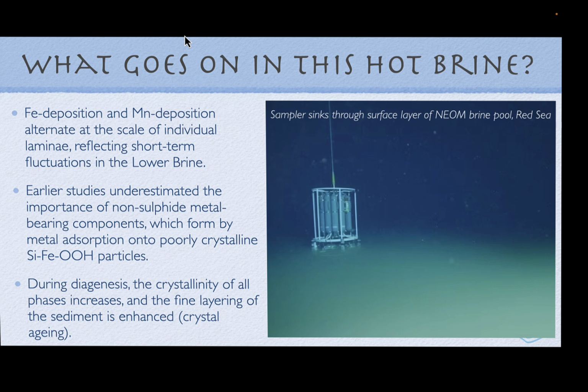It's become obvious in the last decade that earlier studies underestimated the importance of the various non-sulphide minerals as metal-bearing components, where the metal absorption is forming onto polycrystalline silica iron hydroxide particles. Remember back to the brine chemistry, we had some of the highest levels of silica and iron in the bottom brines in the Atlantis II Deep brines compared to the brine pools across the rest of the Red Sea Deep. Now, during diagenesis, these crystals age, they mature, and so the crystallinity of all the various phases increases, and that aging also enhances fine layering in that sediment.